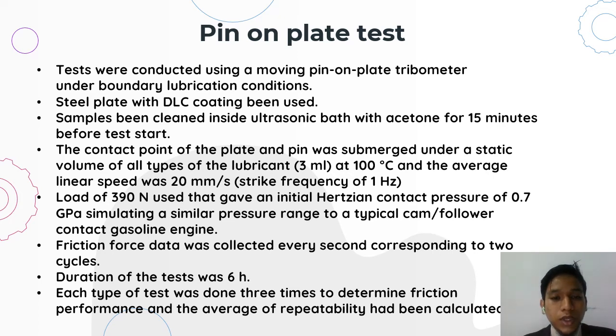Friction force data was collected every second, corresponding to 2 cycles. The duration of the test was 6 hours and each type of test was done 3 times to determine friction performance, and the average of repeatability was calculated.